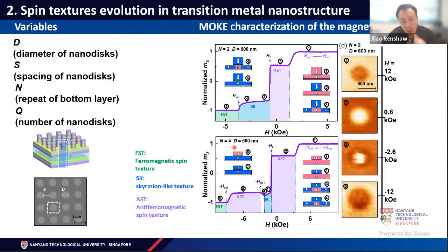If we change the N repetition of the bottom layer, we get similar things. The skyrmion state is slightly smaller. You can see there's an antiferromagnetic state, there's another antiferromagnetic state, and a skyrmion state. So basically, by playing with the N, we can play with the window of the different magnetic states. Of course, those states were also characterized by the magnetic force microscopy images on the right. Here there are 1, 2, 4, 5 magnetic states.